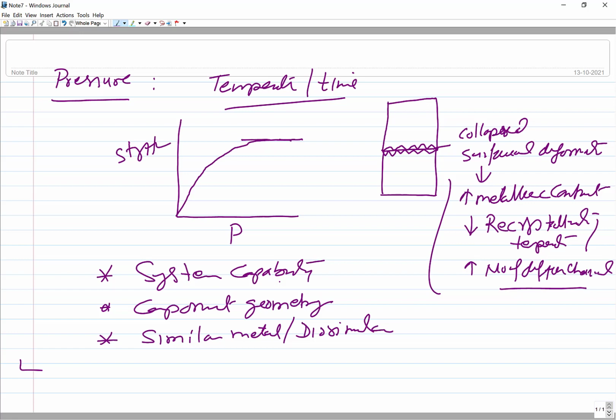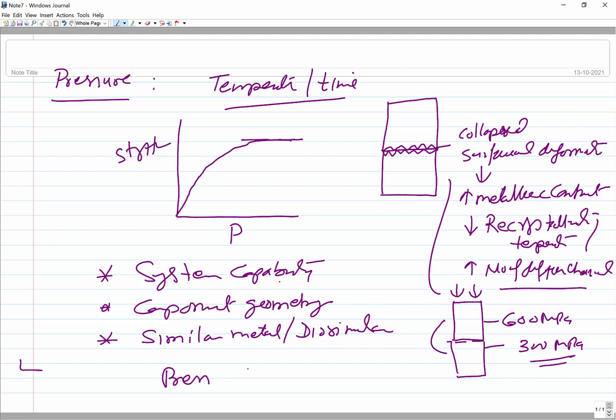The situation is more complex in the case of a dissimilar metal joint, because one component may have 600 MPa strength and another just 300 MPa strength. So if you choose a pressure greater than 300 MPa, then bulging may start, upsetting of the low strength metal may start, and you may lose the geometry of the component under the high pressure. So it is to be kept in mind that whatever pressure is applied should be less than the yield strength of the metal. Otherwise, bulging and deformation of the component can take place.